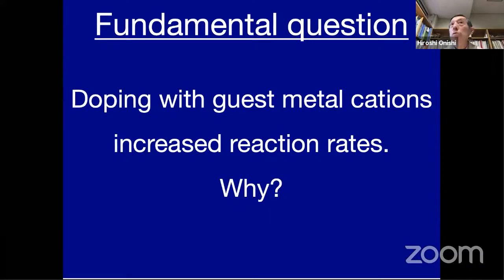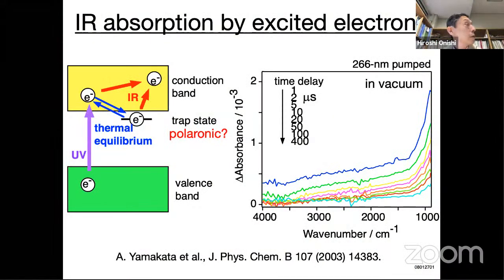So the first question at the starting point is: doping with guest metal cations, strontium cations in this case, increased reaction rates in photocatalytic water splitting. Why? This is a fundamental question to be answered. The first experimental tool was infrared absorption measurement of the photocatalysts. The green area is the valence band of sodium tantalate, and the yellow area is the conduction band. When we irradiate the photocatalyst with ultraviolet light, one electron is excited from the valence band to the conduction band. And this excited electron can further absorb infrared light.